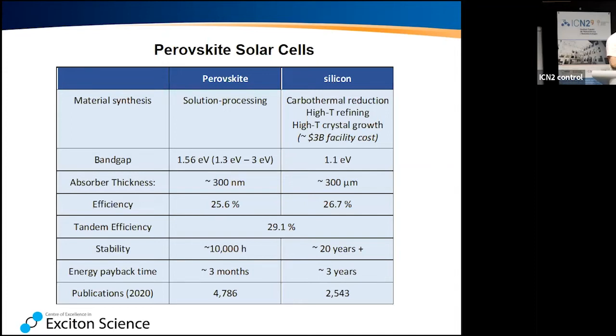The stability is what I typically call the Achilles heel of perovskite at the moment. We have up to 10,000 hours, whereas with silicon, you can easily go to a shop and find a manufacturer that gives you a 20 year warranty for your material. Energy payback times, this is where we can beat silicon. Giving up on this pointer. We have 3 months roughly versus 3 years. That's the time it takes with a solar cell on the roof until you get back the energy that it took to make it. Also very interesting, in 2020, there were about twice as many publications on perovskite as on silicon. So even though nothing's on the roof, on the science side there's a huge interest: twice as many papers.